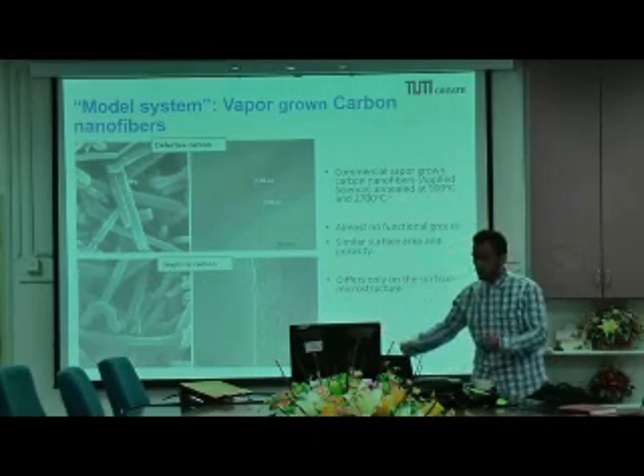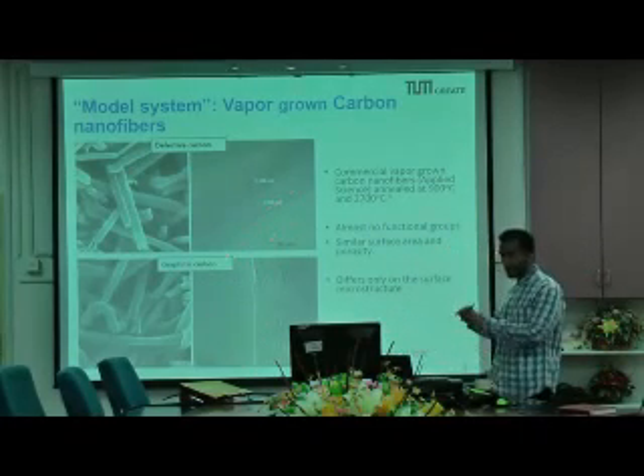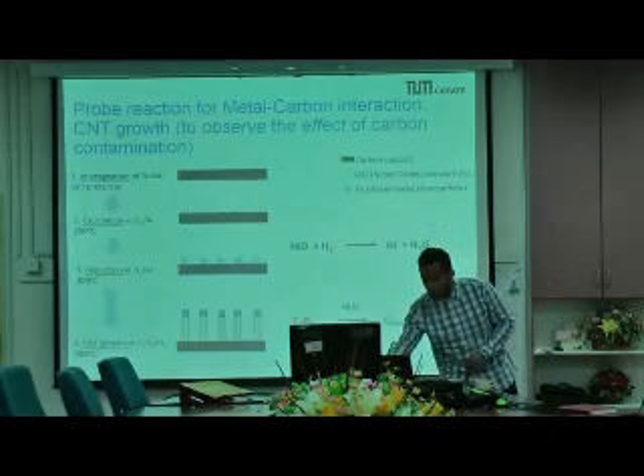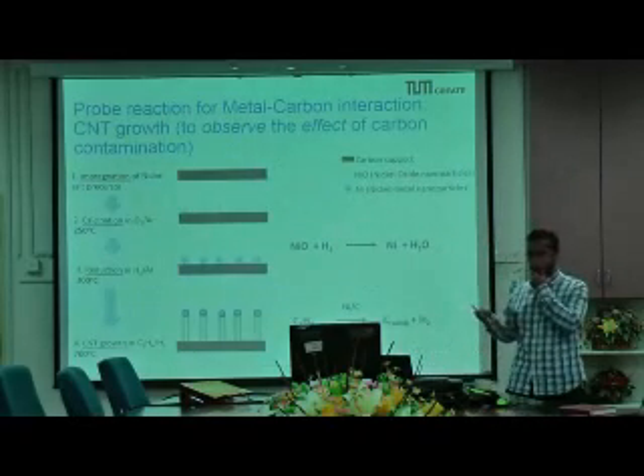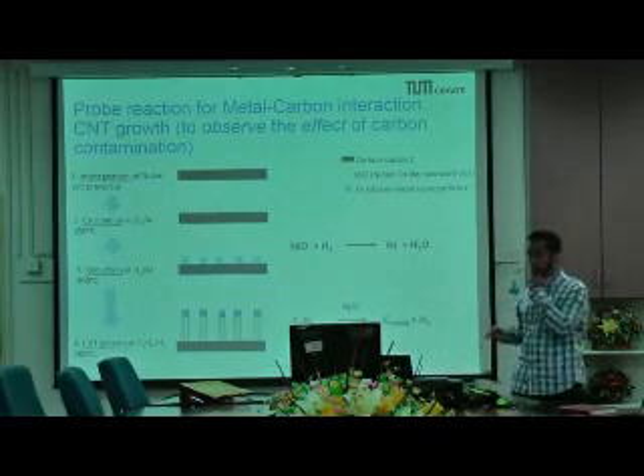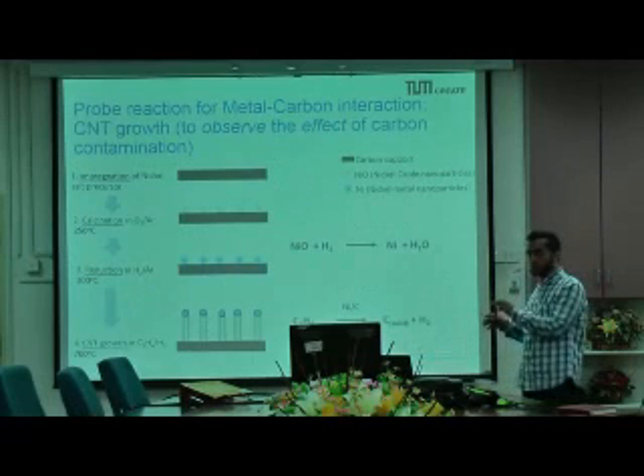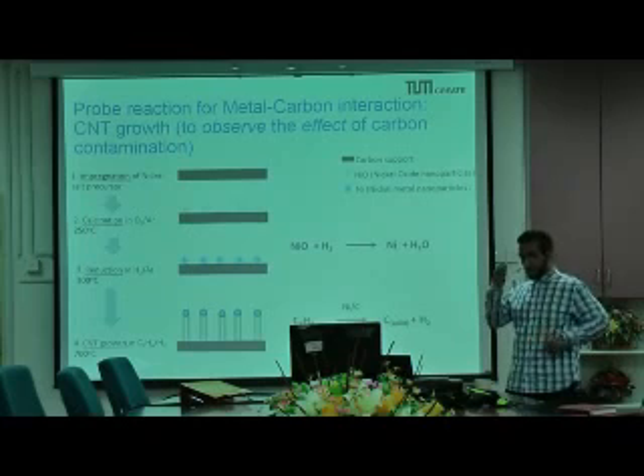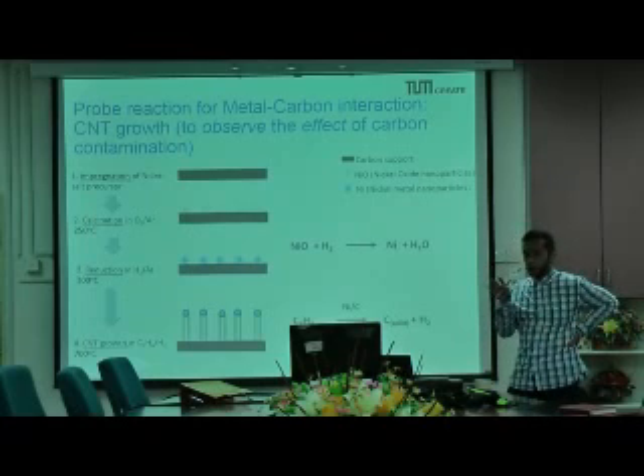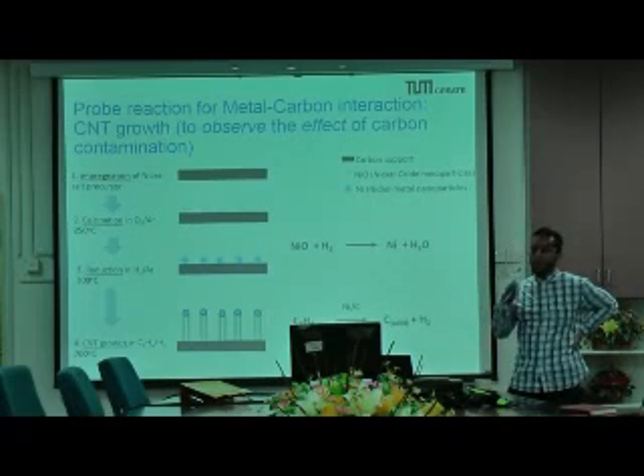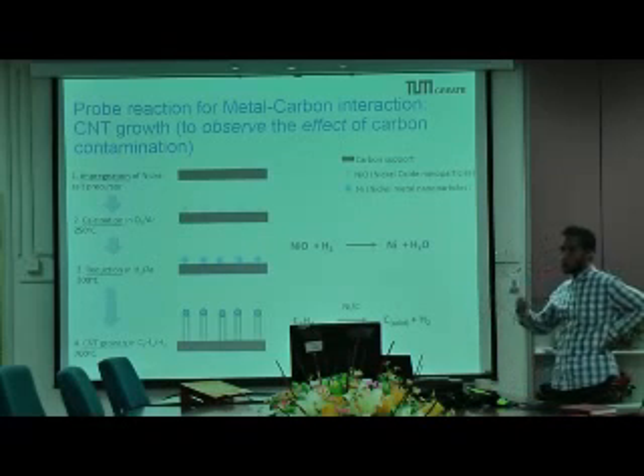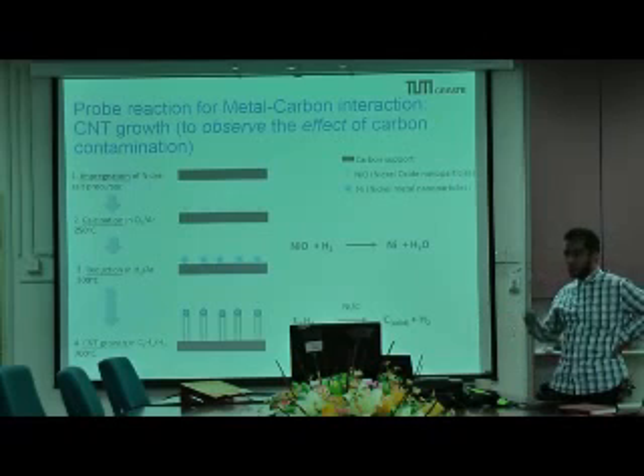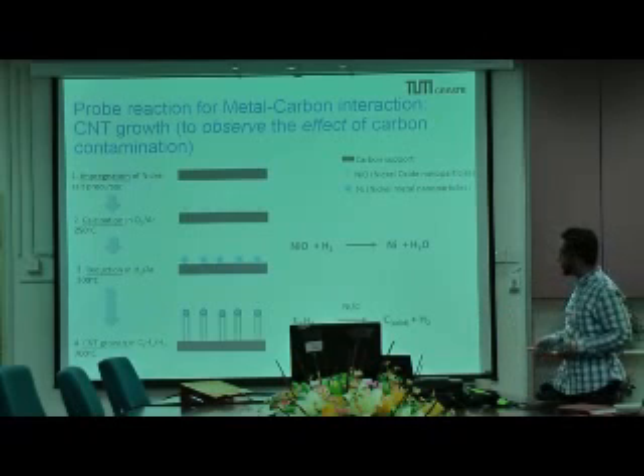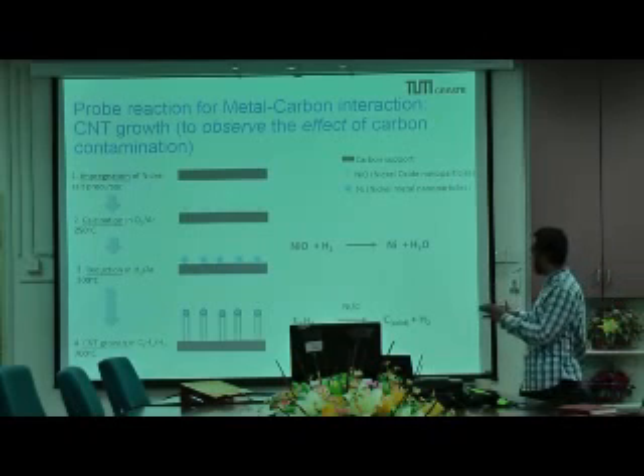So exposing on basal, whereas here is mostly defects or edge sites. So we need a probe reaction. As I already mentioned earlier, the probe reaction we are investigating is carbon nanotube growth. Remember what I said earlier, that we want to investigate carbon contamination. So we want a reaction that is very sensitive to carbon contamination or carbon diffusion on the surface, subsurface, or the bottom. So we choose the carbon nanotube probe.